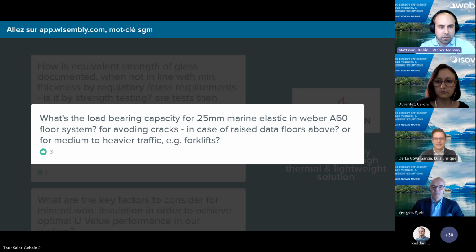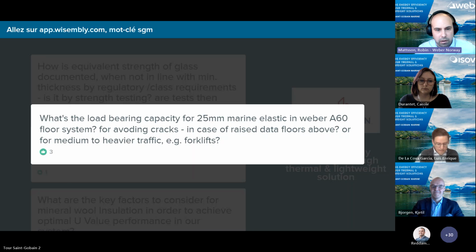Thank you, Luis. It's a very good question. So we have done a lot of mechanical testing for our floating floor systems. For example, one test is a wheel rolling test where it managed to handle 2,200 kilos of wheel rolling traffic without any cracks. And we have also made a lot of loading tests where we also have tested over 2,000 kilos without any cracks. But what is very important is if you're putting the insulation slabs directly on the steel deck, it will help a lot if the steel deck is leveled to avoid cracks in the system if you have areas with a lot of load.